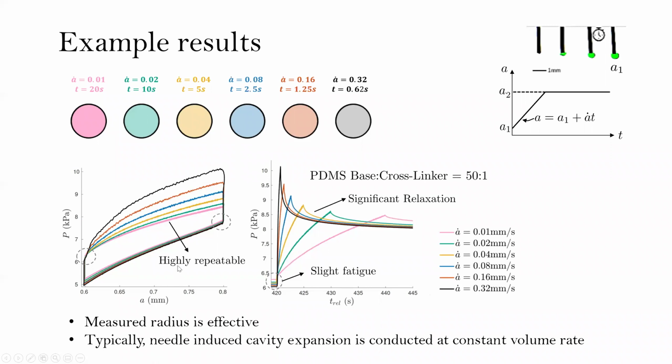One thing I want to emphasize is that one key aspect of the loading protocol that enabled us to visualize this viscoelastic effect is the fact that we control the cavity expansion rate, whereas most cavity-based methods, including cavitation rheology and our previous VCC tests, used a constant volume rate injection. I will later show why that might not be conducive to elucidating this viscoelastic response of the material.